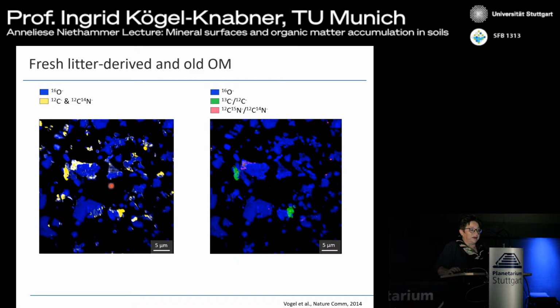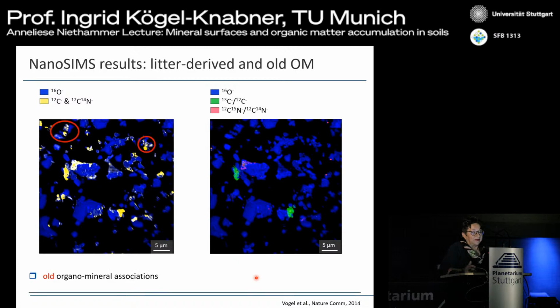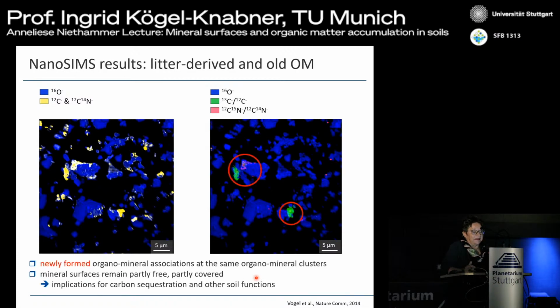Again, this is the old carbon here, and then if we look at the 13C and the 15N, the green spots and the pink spots, you see that, again, this is very heterogeneously distributed and found only in specific spots. And what we also see is that this newly formed organic matter is in the same organomineral clusters that already had old carbon present. So the new carbon is not distributed homogeneously, but it is formed only at specific spots.